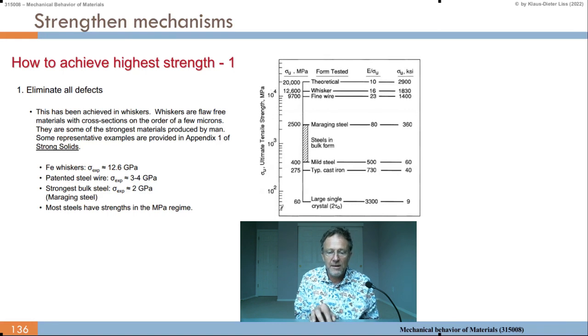And in the single crystal, once we have a dislocation per area, per volume, the surface does not play so much of a role, and that's why the large single crystals have a small UTS. If you compare it, so 1 over UTS times the elastic modulus, we get those numbers here, and there we see the smaller the better.